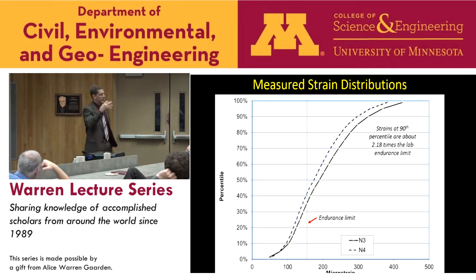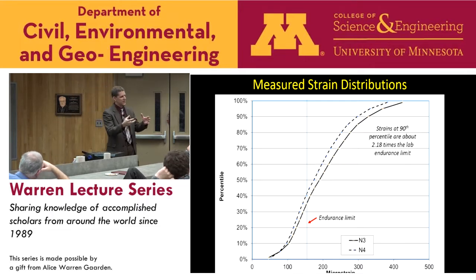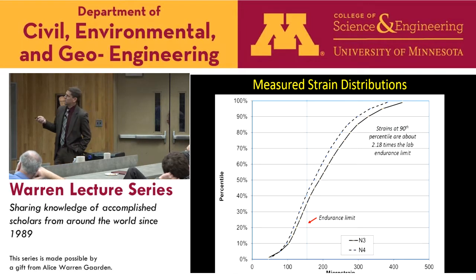Now, while we're doing all this testing in the field, we also take these same mixes in the laboratory, and we measure all kinds of properties. One of the things we measure is where that endurance limit is. What is the strain level below which we don't have cracks developing? In the laboratory, that came in at about 150 microstrain for both of these materials. One was polymer modified, one was unmodified.